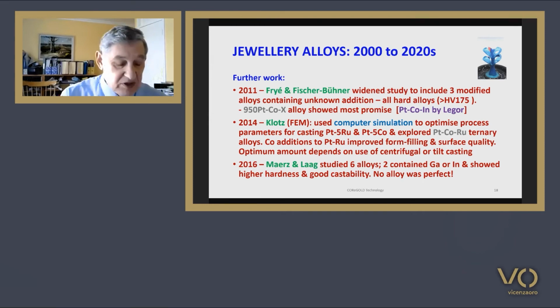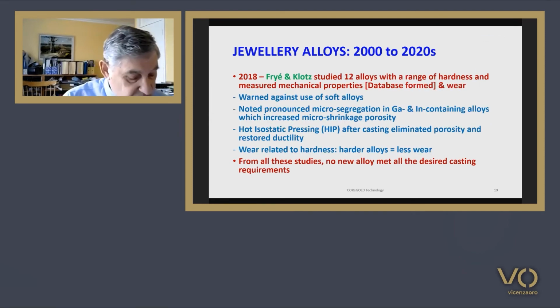The largest range of alloys was studied by Frié and Klotz in 2018. They also measured the mechanical properties and wear resistance of castings. They warned against the use of soft alloys in cast jewellery and noted pronounced microsegregation in gallium and indium containing alloys, which increased micro-shrinkage porosity. Hot isostatic pressing treatments after casting eliminated porosity and restored the ductility. They also noted wear was related to hardness, harder alloys wearing less. No new alloy met all the requirements for casting.